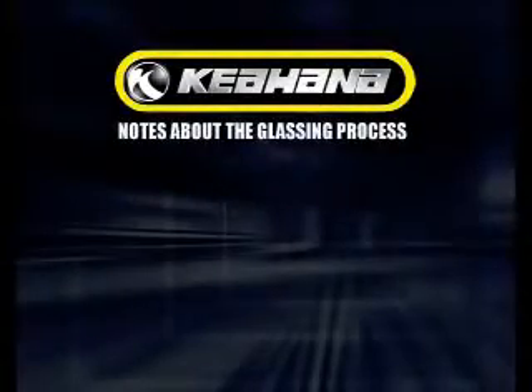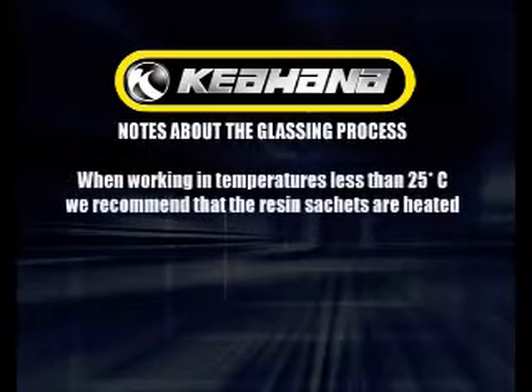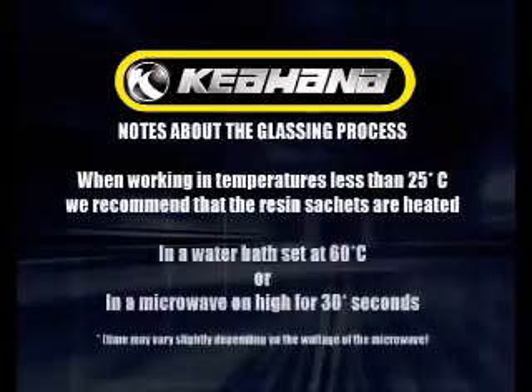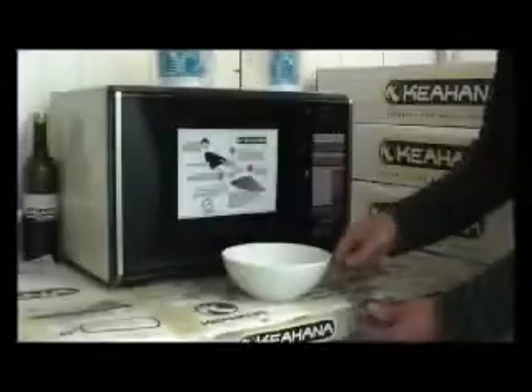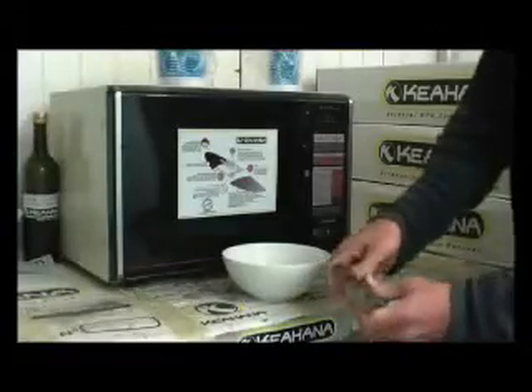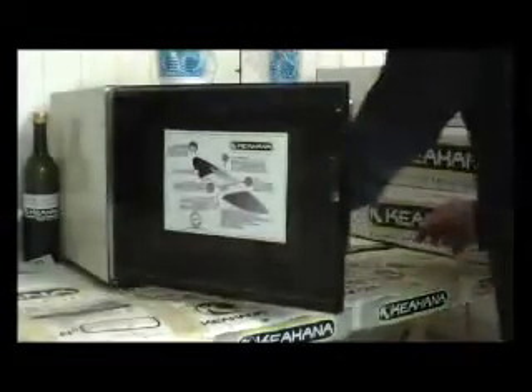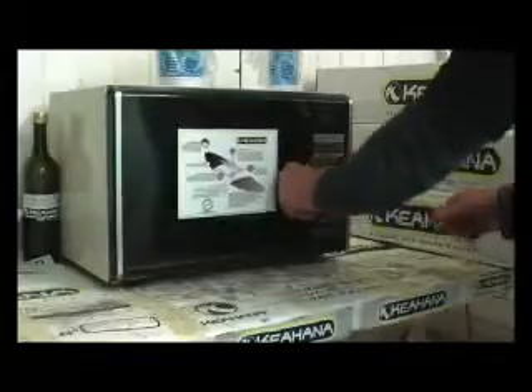Notes about the glassing process. When working in temperatures less than 25 degrees, we recommend that the resin sachet is warmed in a water bath set to 60 degrees, or by using a microwave for 30 seconds on high. Heat up just the resin sachet, not the hardener pot. Warming the resin makes it thinner and easier to work.